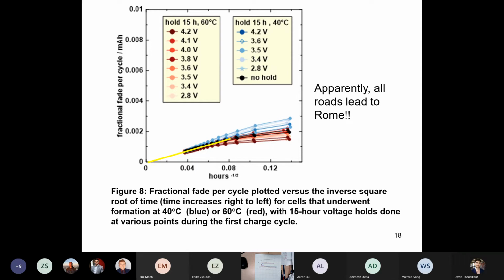And you could ask the question in our lab, why do we do all our formations at 40 degrees C the way we do it? I mean, we do it for consistency, but we could certainly change. And sometimes when we have an imminent power failure, I tell people to just do the formation at C over 10, not C over 20. It doesn't matter. In the end, you're going to get the same thing.